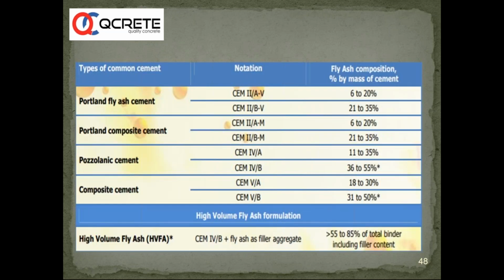So this table is very interesting actually. From BS specifications, you have different kinds of cement, types of cement, where a pozzolanic cement can have between 36 to 55%. A composite cement can have a fly ash content of about 31 to 50%. So different combinations have been given, different choices have been given to the customer. So what I'm trying to talk about is that you have a choice to make use of fly ash, and there is classification available